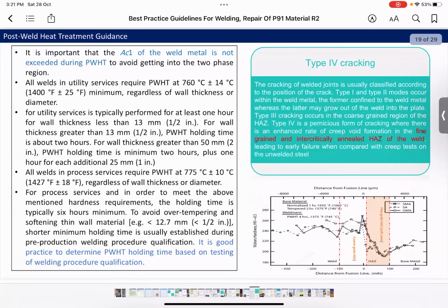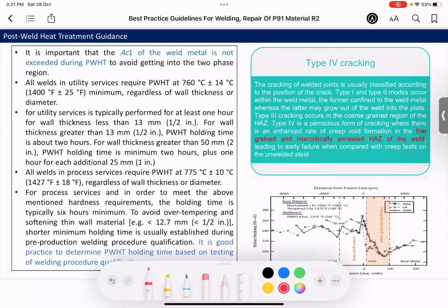So the type 4 cracking, I spoke about type 4 cracking. The cracking of the weld joint is usually classified or categorized according to the position of the crack. So what do we mean by type 4 cracking? Type 1 and type 2 are within the weld metal, type 3 in the coarse grain area, and type 4 is in the soft or fine grain area, as shown here. This is the area where the hardness sharply drops, making it susceptible to cracking, or it will affect its creep strength and creep resistance during service.